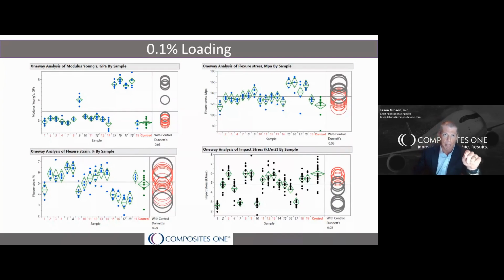So let's take a look at the impact results in the bottom right corner for those same 5 samples and see if they affect the toughness of the resin. You'll see that samples 15, 16, and 17 are all in gray. That means that they significantly reduce the toughness of the base resin. That's not good. But both samples 9 and 18 are shown in red, meaning that their impact on the toughness is statistically negligible, which is good news. It means that out of the 17 samples tested, we have 2 that significantly improve the flexural modulus and strength with negligible impact on the toughness of the system.